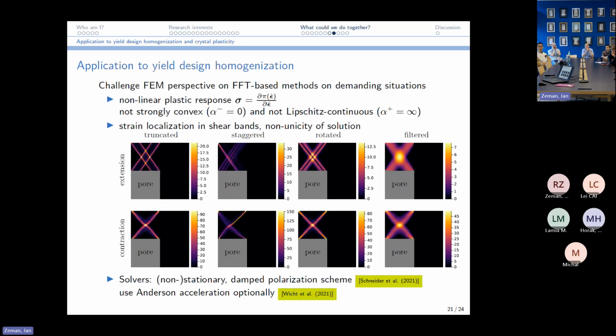So yeah, some potential applications. I'm still working on this yield design homogenization, and it's a pretty tough topic because this plastic potential is really nonlinear and it is not strongly convex, and in the regions where you do not have this plastic strain, you would have like an infinite stiffness, tangent stiffness, secant stiffness, sorry. So also you have non-uniqueness of the solution for the strain, but the stress is unique. And so depending on which type of discretization you use, here on the different columns, your response can be very different. And also, if you change the reference medium of the FFT-based method, you would change also the response. So there is much investigation to do with that.